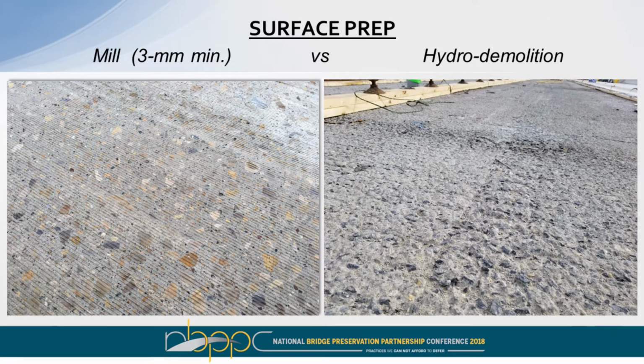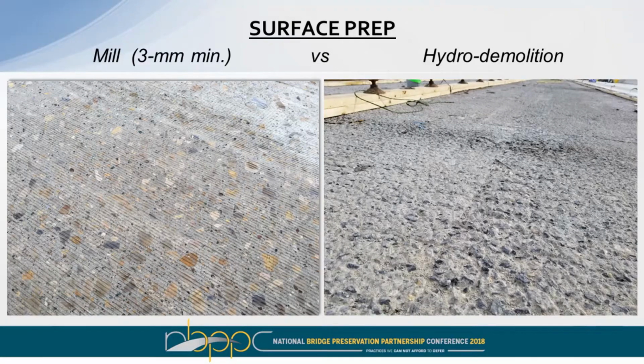And generally surface prep, exactly like the last presenter talked about, you can do this on a milled surface, you can do this on a hydro demoed surface. The hydro demoed surface tends to be preferable in the sense that it's going to bust away whatever poor concrete is there. With a milling effect, you might not get everything, and actually we saw this on the Iowa job. They did a mill, which is shown on the left photo. They poured the overlay, and then after everything was done, they went back and did a chain drag, and then they found that there actually was some delamination. It wasn't between the UHPC and the substrate, it was underneath the rebar where the poor concrete had not been fully removed.